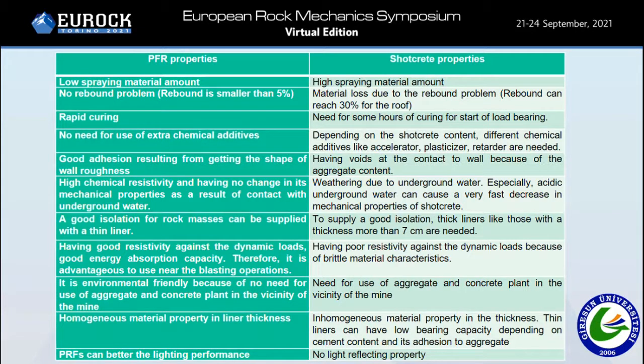Tensile strength values of PRF specimens were found to be in the same class with that of the shotcrete materials. Even though the load-bearing performance of the PRF liners was found to be lower than the shotcrete liners, its load-bearing capacity is notable in terms of supplying stability against the potential rockfalls. Stiffness values of the PRF liners are significantly lower than those of the shotcrete liners. This situation means that PRF liners are not preferable for poor rock masses, which need the use of stiff supports. It should be noted here that the PRF liner material is evaluated for its potential use as an alternative to thin primary shotcrete liners, not permanent concrete supports such as concrete liners in tunneling.